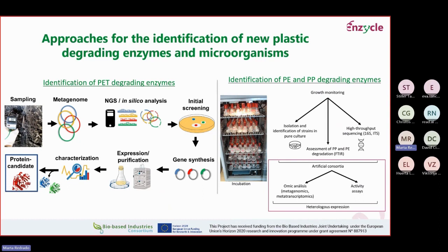So we aimed for the identification of microorganisms, also microbial consortia, that were naturally growing or present in, for instance, polyethylene and polypropylene. So what we did is we isolated these new strains from polyolefin residues. We isolated these bacterial strains and consortia, and we enriched microbial cultures in minimal media containing polyolefins as sole carbon sources, to promote the development of these particular microbes or microbial consortia able to use these plastics as carbon source.